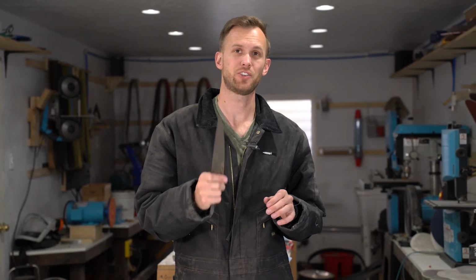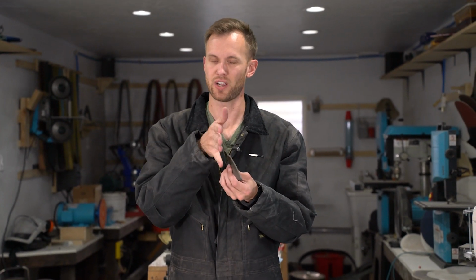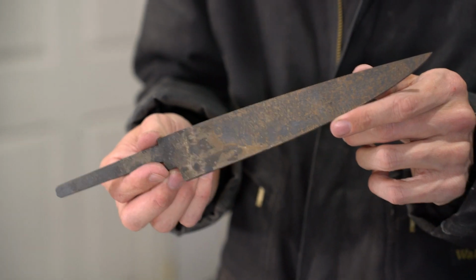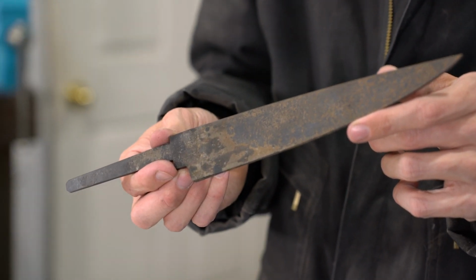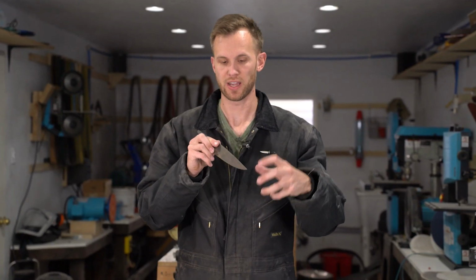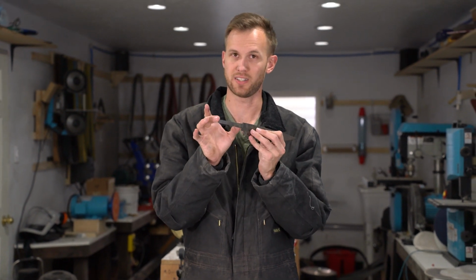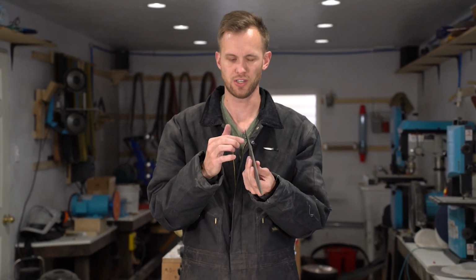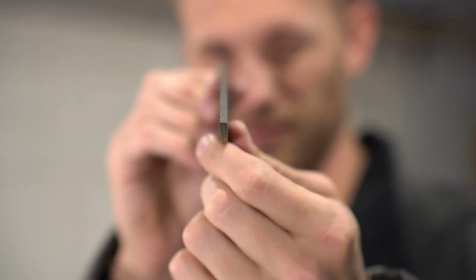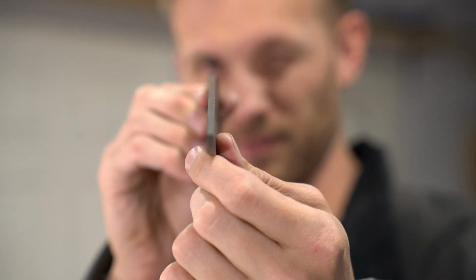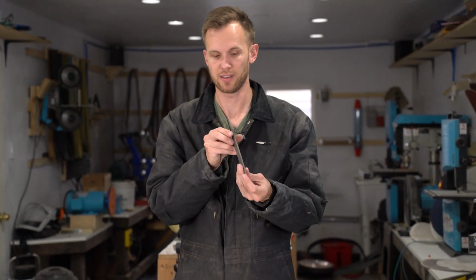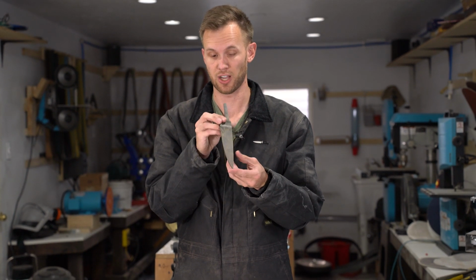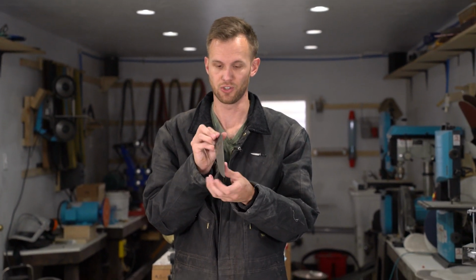All right, the knife has been heat treated. After getting it hot and quenching it, we then did the tempering cycles. Actually, I ended up doing 3, because while it's tempering is a time that you can try and fix warps. If you counter bend the knife just a little bit while heating it up to the tempering heat, sometimes you'll get a change in it. I had a slight warp in the tang, and then after the first 2 heat treatments, the tip was just angled off a little bit. So I did a third one where I tried to fix some of that warpage, and I think it did a pretty good job. So we are very close to straight.